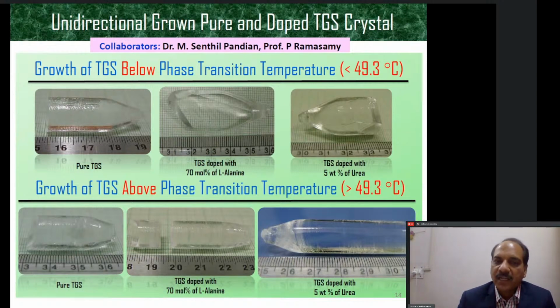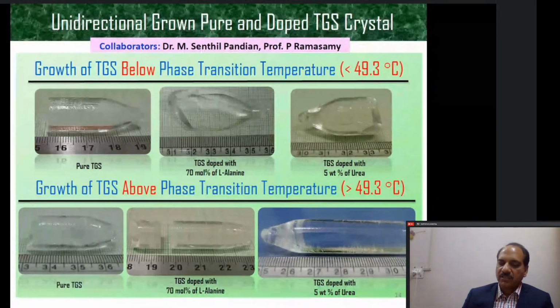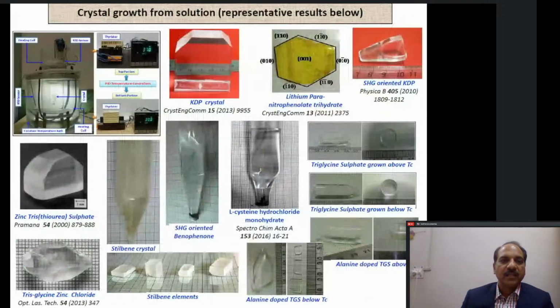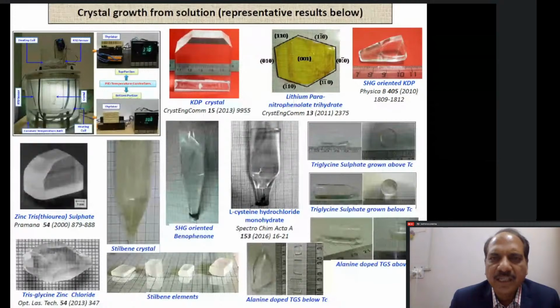TGS doped with L-alanine, which is doped TGS to enhance its ferroelectric properties, which are used for IR detection applications. And similarly we also grew TGS above its phase transition and below its phase transition temperature by doping urea, because that also enhances some of these properties. And these are 6 crystals which were grown, and these crystals were cut and characterized, and their figures of merit were measured. All this work has been published in excellent, outstanding journals. And in fact, these are some of the representative results and some setups which I am showing, which we have been able to grow using both.